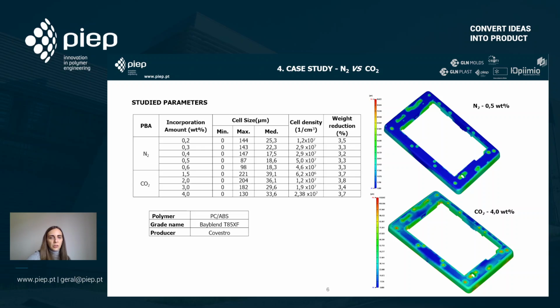So by analyzing the results we had, we could see that weight reduction was not a very variable factor, a response that we could actually vary. And it is important to note that in this phase, there is not an injection molding equipment, so a lot of the process is still being defined, so there is not an optimization. So weight reduction values here are still low. And we have to center our study in the cell size and cell density.